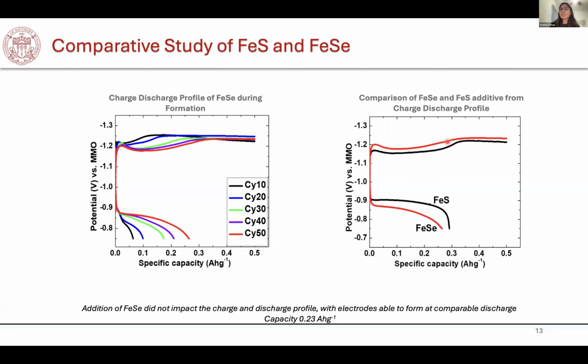you can see that the polarization curves are quite similar. The features are quite similar. That indicates that this additive does not introduce any significant electrochemical changes into the electrode and can serve as a good alternate additive. And moving on, the other way I tried to introduce this additive was through the electrolyte.